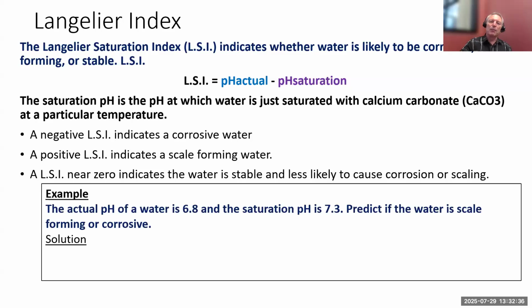And I'm going to give you an example here. We have a water and we measure the pH. The actual pH is 6.8, but its saturation pH is 7.3. Predict if it's going to be scale forming or corrosive, and here's how we would plug it in. We'd have a negative number because the actual number is 6.8. The saturation pH is 7.3. 6.8 minus 7.3 equals a negative 0.5. So that means it's corrosive water.